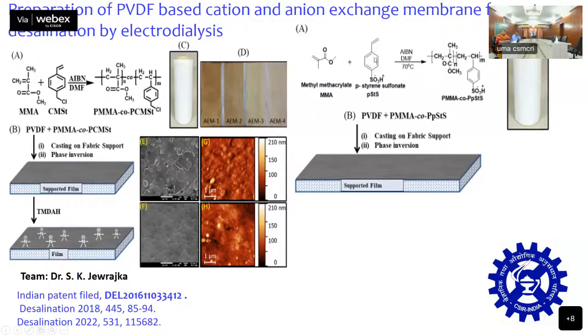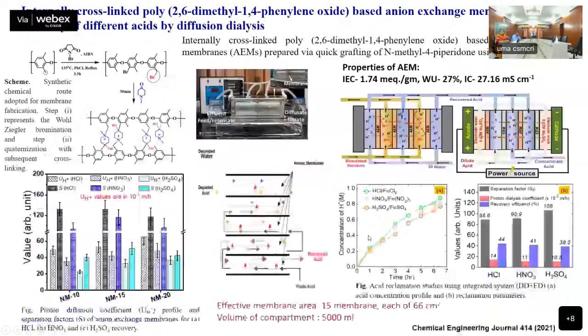The cation exchange membrane is prepared from the copolymer of methyl methacrylate and styrene sulfonic acid, and this copolymer contains a sulfonic acid moiety, so we don't need any post-sulfonation reaction. Then the copolymer is mixed with PVDF, and that membrane is cast by the immersion process. So this is patented and supported by publication.